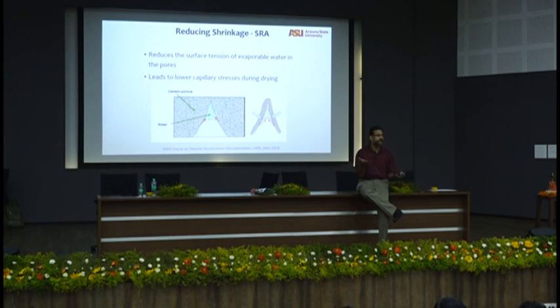What it does is a very simple thing. You know what the surface tension of water is? Anybody know off the top of their head? No? Surface tension of water? PhD students should know this number. But I still remember the old British units, 72 dynes per centimeter. So you can convert it to newtons per meter, whichever way you have. So that is the surface tension of water. And remember the capillary pressure equation which I showed you earlier. Does anybody remember it without looking at it? P is equal to 2 gamma over R. What is gamma? Surface tension.